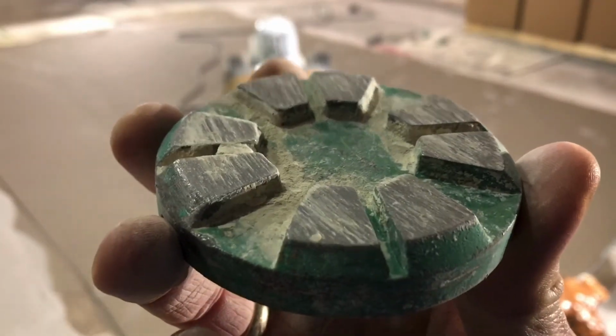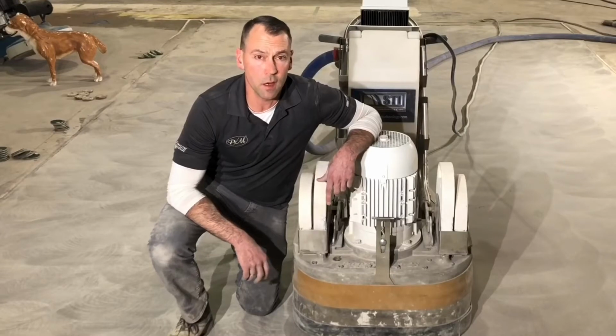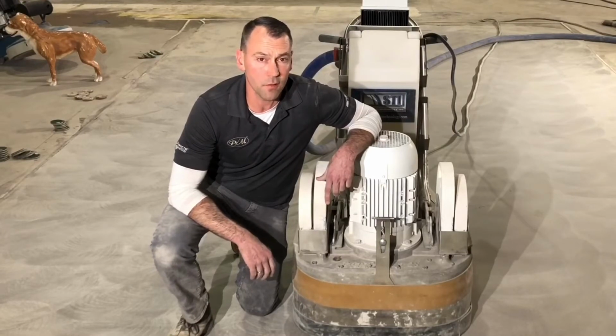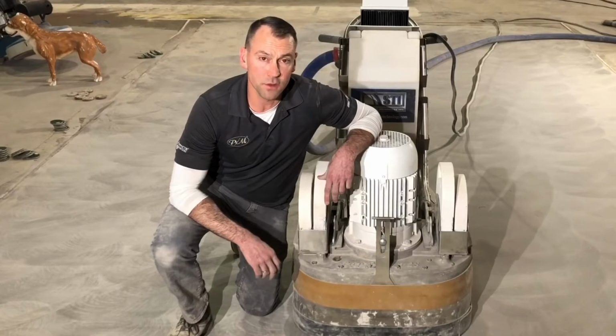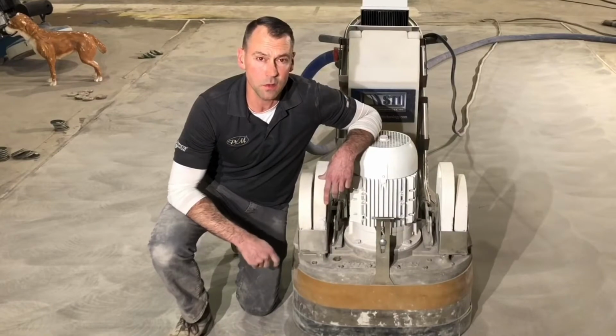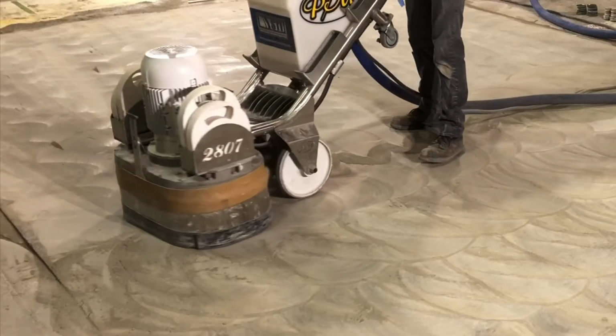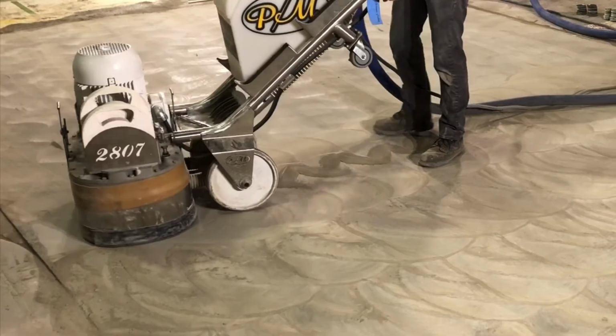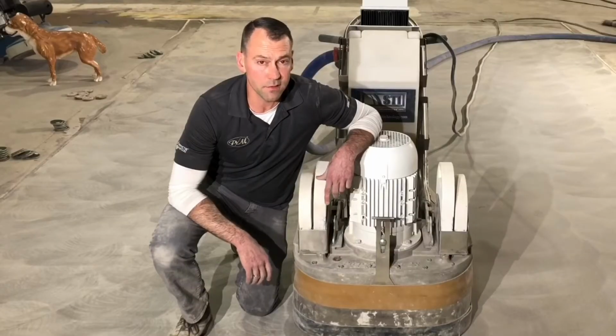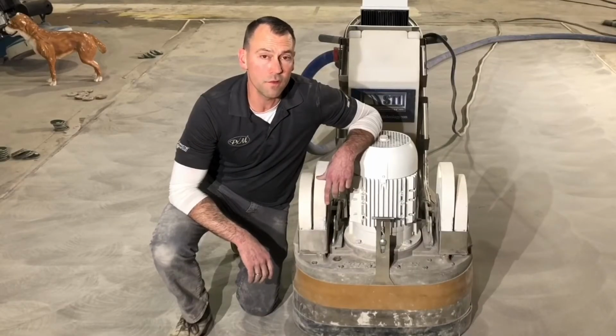Now this particular floor, which we learned as we ground, is actually meant to be installed at 1/2 inch, but finished off at about 3/8 of an inch. So that means 1/16 to 1/8 of an inch is going to be removed. It's something that's special for this particular product, but nonetheless, in order to get the reveal of the aggregate inside the mix to be exposed, that's what was required. As we started to cut on it with 40 grit, we found out that they just weren't aggressive enough to break through that cap and remove that much material.